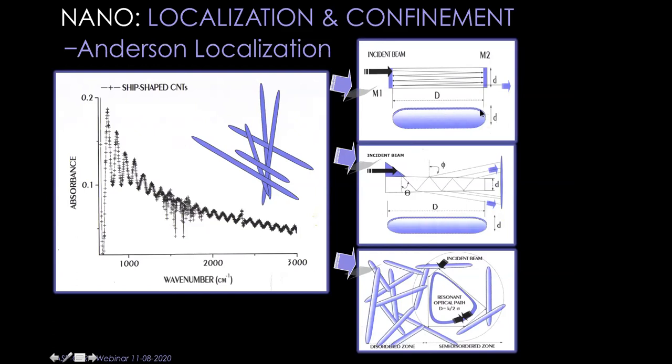and by the way, the carbon nanotubes, if they are single wall, there is no closure here. There is no such mirror. So when you do these calculations, you will find out that if you consider this model, some of the carbon nanotubes act like perfect resonators, like a Fabry-Pérot resonator, as in classical optics. But you will find out the contrast of these resonances, which means the minimum here to the maximum, or the minimum here to that maximum.